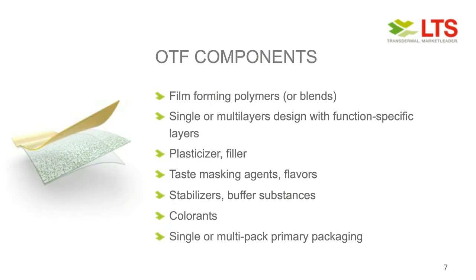So our thin film components are usually a very long list in the formulation. But all these different formulation types, the components, the excipients, have a distinct feature. And the first thing is the film-forming polymers or polymer blends, mainly water-soluble polymers. One of the most used examples is HPMC. The film designs can be either single or multi-layer, with different layers having different functions. To achieve the right film properties, we have to add plasticizers or fillers in order to make the film stable and not sticky, for example. And since most APIs do not come with a great taste, so very often are bitter, taste masking agents have to be added, or flavors or sweeteners. Of course, just to fill up the list of excipients, stabilizers are also very important, and we can also add buffer substances in order to create a local pH in the oral cavity, which improves the absorption as well.